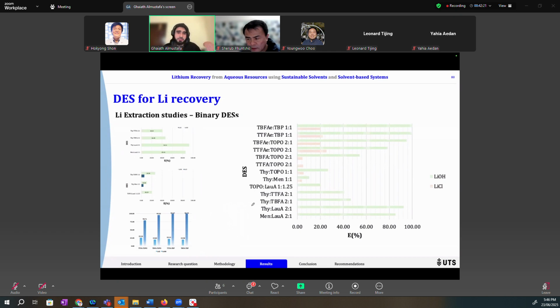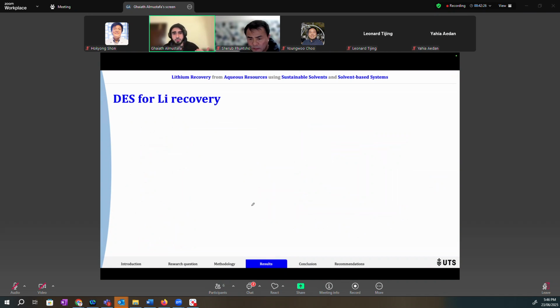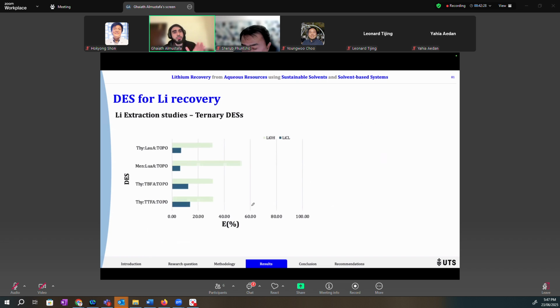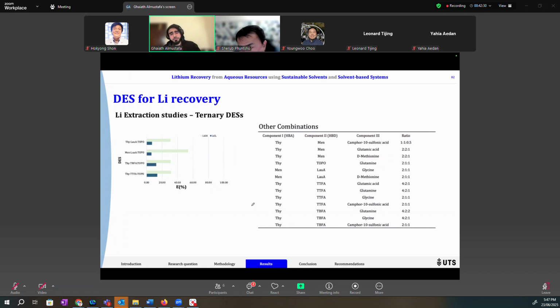Of course, we used previous combinations to compare with previously reported combinations, and then we modified them later on in our own method with ternary DESs. So we chose different ternary DESs as well, and we played around with them in order to see how we can enhance the extraction efficiency. Of course, we faced some difficulties here where we actually decreased the extraction efficiency, and that was due to the purity of the additive that we used. So we have to check the purity properly.